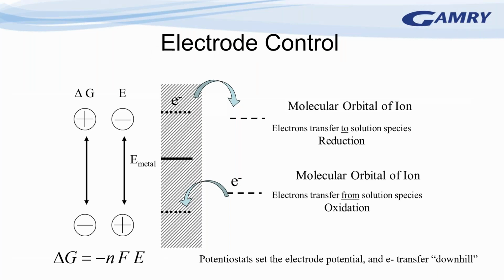So the potentiostat is used to control the electrode by raising or lowering the energy of the electrons in the electrode. It sets the potential so that electron transfer can go downhill. In the case of reduction, we need to raise the energy of the electrons so that they can pass to the molecule in solution. And in the case of oxidation, we need to lower the energy of the electrons so that electrons can be transferred into the electrode. And you can also think of the electrode potential in terms of the thermodynamic state, like delta G.